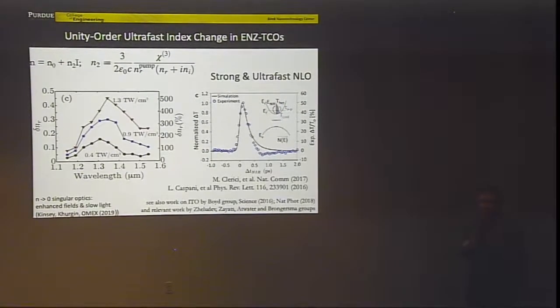You could ask, what was the physics behind this? Why do you have all this dramatic change? There are 2 things. First of all, I should admit there is no complete understanding, but there are some guiding ideas. First one, the displacement D, which is epsilon times E, the normal component, should be continuous across the interface. If I go from air to material, in air epsilon is equal to 1. In my material, epsilon is close to 0. But epsilon E should be continuous. So if epsilon goes to 0, the local field gets dramatically enhanced. You have this confinement induced by the fact that epsilon goes to 0. You have field enhancement because epsilon goes to 0.